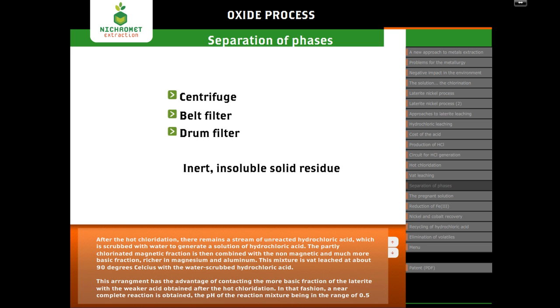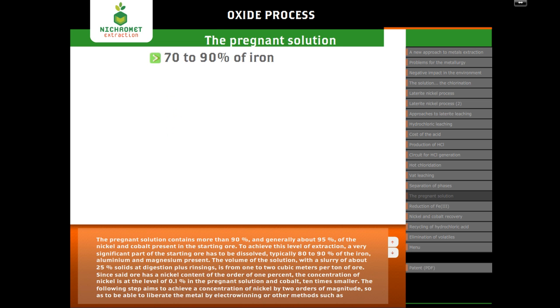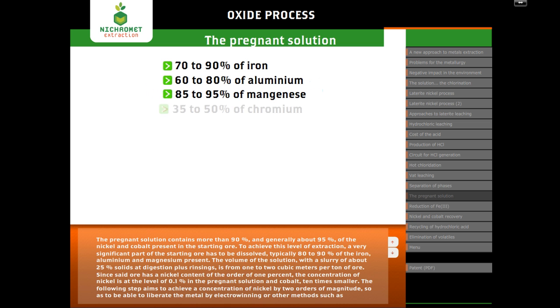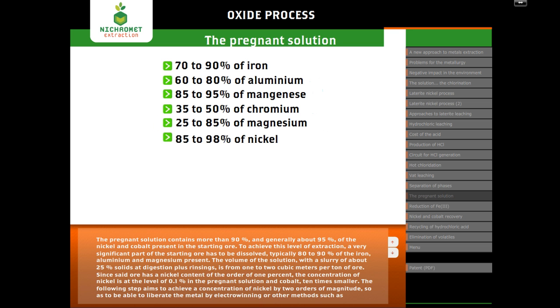It is essential to rinse the cake on the filter by at least 2 displacements, so as to recover all of the leached material and leave a waste containing no soluble entities and no capacity for the generation of lixiviates. The pregnant solution contains more than 90% and generally about 95% of the nickel and cobalt present in the starting ore. To achieve this level of extraction, a very significant part of the starting ore has to be dissolved. Typically, 80 to 90% of the iron, aluminium, and magnesium present.